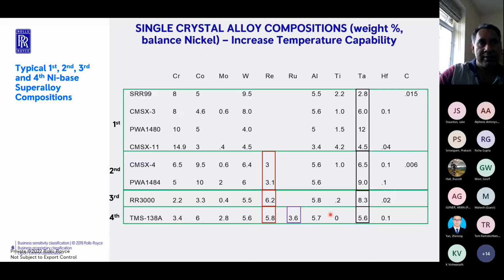But the point is you're adding ruthenium. Now, if you think that rhenium was an expensive element in its own right, ruthenium is a lot more expensive. So again, fourth generation alloys are extremely expensive. And just to give you a magnitude for cost, this was going way back about 10 years ago, the cost per kilo of, for example, a third generation alloy was of the order of a few £100. It was nearly 8 times more expensive if you used TMS 138A, which is a Japanese alloy.